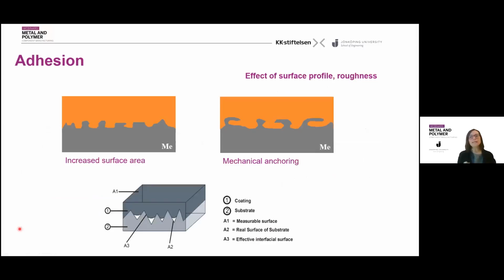In order to increase and improve adhesion, being such an important factor for durability, we have a few strategies. Because the number of bonds depends on how big the area of interaction is, we can modify the profile of the aluminum surface to make it rougher, so the real surface area is increased compared to the nominal one. This way, there is more space for forming a higher number of bonds, increasing adhesion. Remember, by roughening the surface, we're really increasing the real surface area and the total number of bonds.